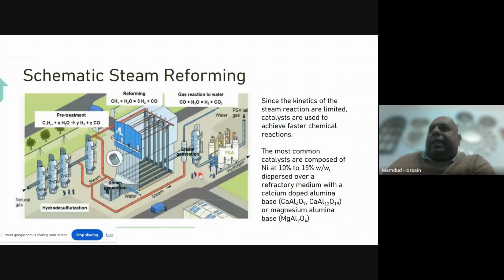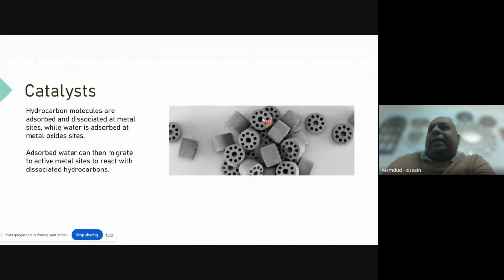In this steam reforming process, the main chemical kinetics is limited by the catalyst. The type of catalyst gives you the faster chemical reaction. So if you look at this chemical reaction happening here, we need to have a catalyst, and this type of catalyst is actually nickel catalyst, used at 10% to 15%. This is dispersed over an alumina based support. So you have a refractory medium which is an alumina based support structure. You embed nickel on top of this structure, and that acts as a catalyst. So these are some of the figures of catalyst here.